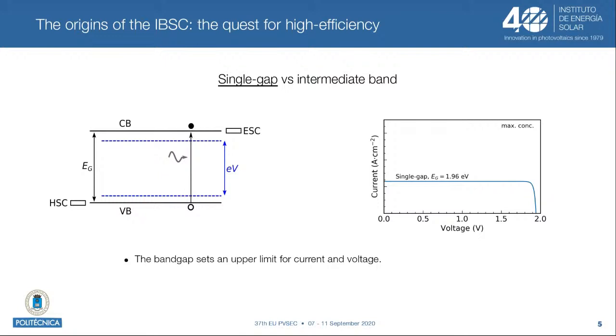This is a graph of the efficiency versus band gap for maximum sunlight concentration for the intermediate band solar cell, which is in red, and the single gap solar cell, which is in blue. Let me just briefly comment that this calculation has been made assuming a very narrow intermediate band. If one takes into account the width of the intermediate band and plays with that parameter, you get different scenarios and slightly different numbers, such as in the so-called photon ratchet intermediate band solar cell. But let's say in the classical picture, we get higher than 60% efficiency for band gaps between 1.5 and 2.5 electron volts, to be compared with the 40% for a single gap solar cell at maximum concentration.